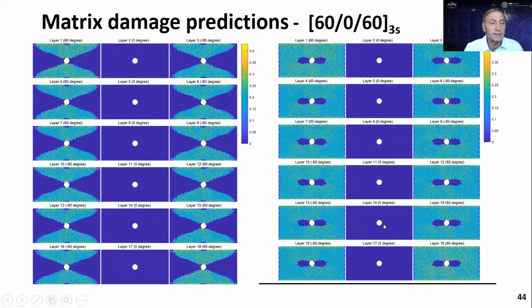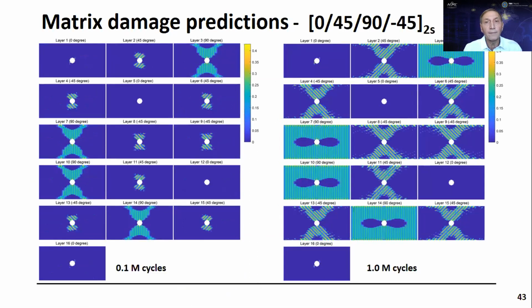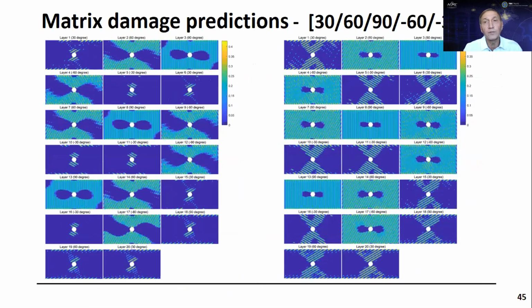And you will see the same kind of damage patterns in the next laminates. So in this particular case, you have 60, 0, 60. And again, here you see the damage pattern is taking place along the direction of the fibers, and the 0 degree plies basically take up all the load, there isn't really much damage taking place. And let's see, the next one, we don't have any 0 degree plies here. It's very soft. And again, I'm showing you some damage maps here, nothing different.